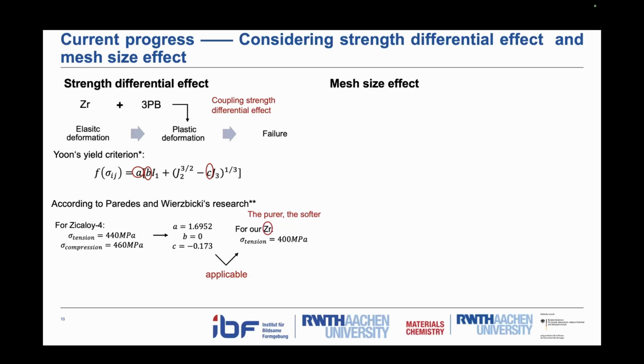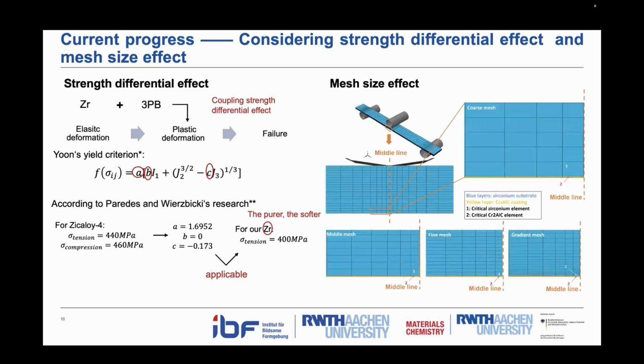Then we also investigated the mesh size effect because there exist significant differences between the thickness of the coating and substrates. And we actually adopted 4 types of mesh size, which are coarse, middle, fine, and gradient. And we compare the results of the critical stress states at the critical moments of the critical elements. And we figure out there exist no significant differences. And to increase the computational efficiency, the coarse mesh was finally adopted.